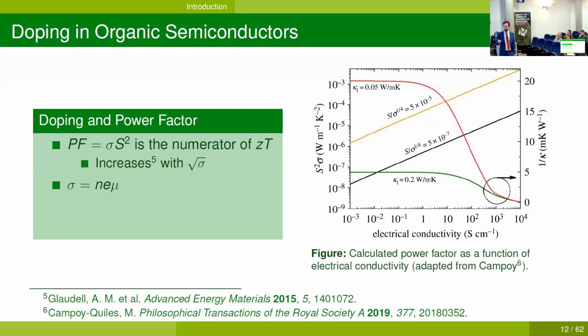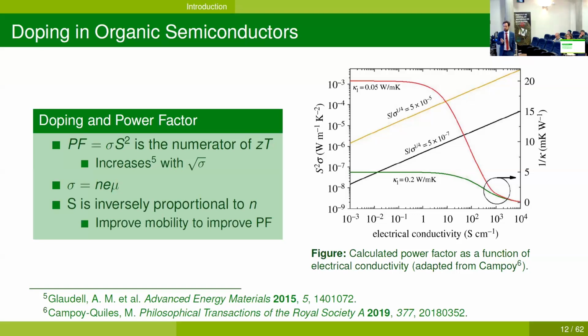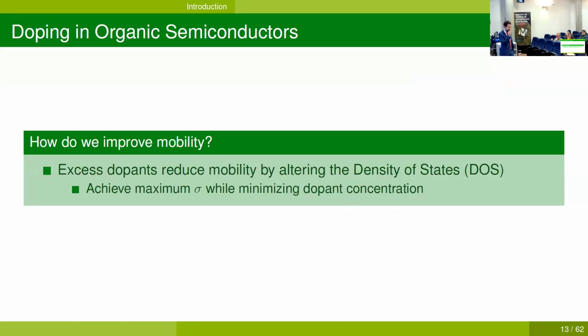And if we recall, the electrical conductivity is nothing but the product of charge carrier density n, elementary charge, and mobility mu. But the Seebeck coefficient is inversely proportional to the charge carrier density n. Therefore, we have no other choice than to improve mobility in this expression to improve the power factor. And how do we improve mobility? For example, we know that excess dopants reduce the mobility by altering the density of states. Therefore, we need to achieve maximum electrical conductivity while minimizing dopant concentration.